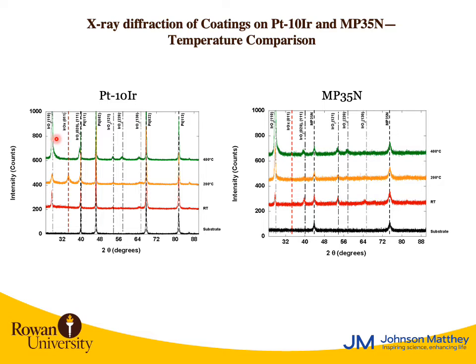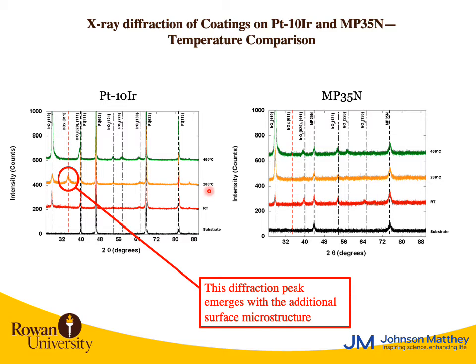But what's unique about the 200 degrees C is there's this reflection here, the 011, which is not present in the 400 or the room temperature depositions. And there's only a hint of it shown here at the 200C and the MP35N, indicating that it's possible that those platelets are that orientation of crystal of the iridium oxide.